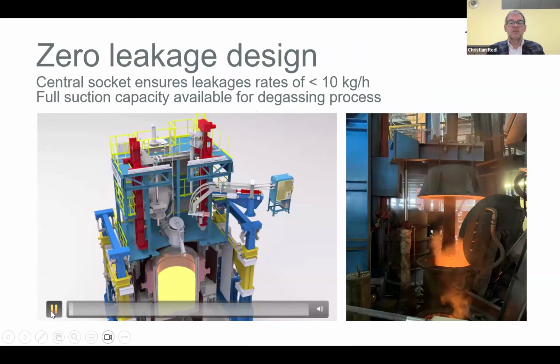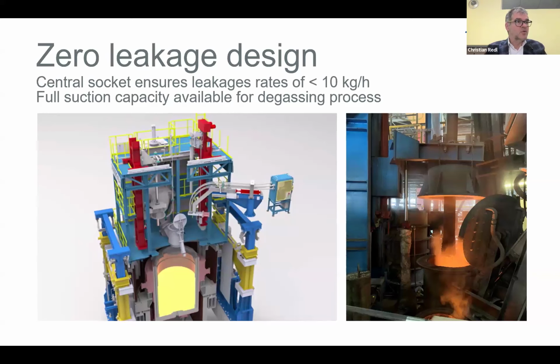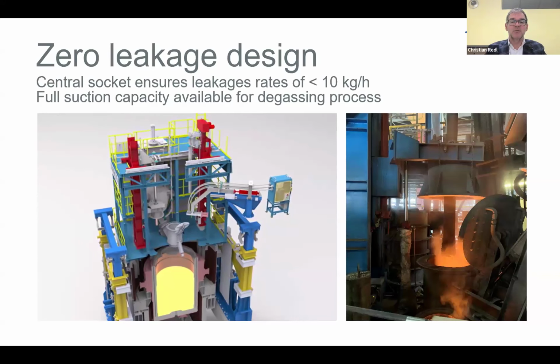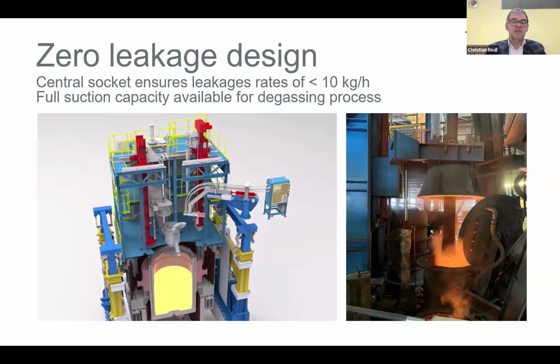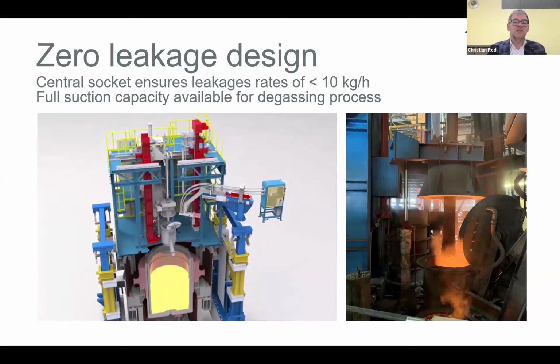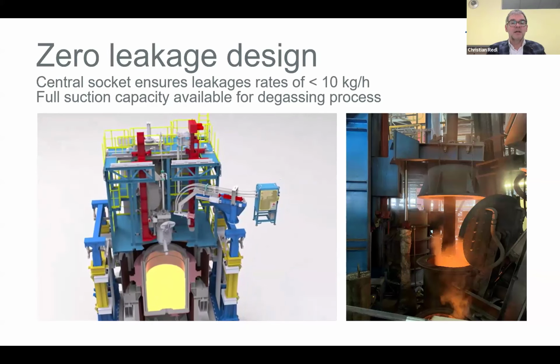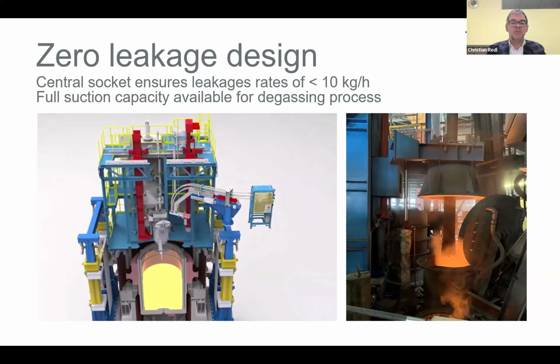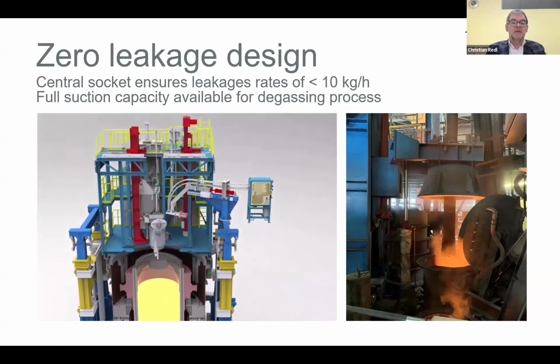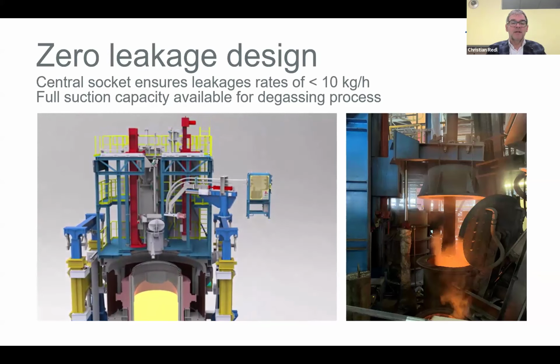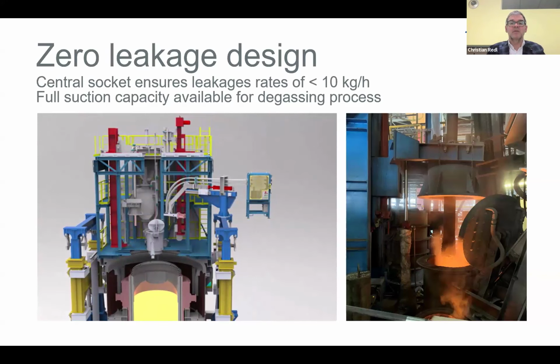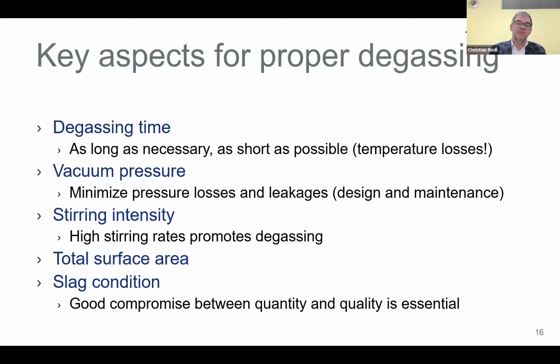We have developed over the last years what we call a zero leakage design. So we want to avoid a lot of openings in the cover, which we have to seal during the treatment. Therefore we are going for, you see here, this central socket. Through the central socket, we can insert the oxygen blowing lance if we have a VOD. We can make wire feeding and temperature and sampling measuring through only one feeding point. Therefore, the leakage rates can be as low as 10 kilograms per hour, which allows a smaller design of the vacuum pump, a very short pump down time, and very low final vacuum pressure.